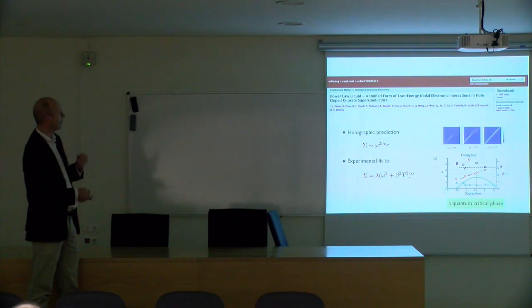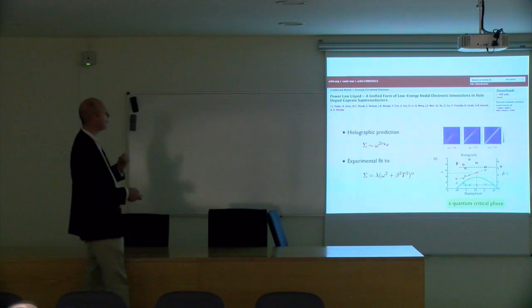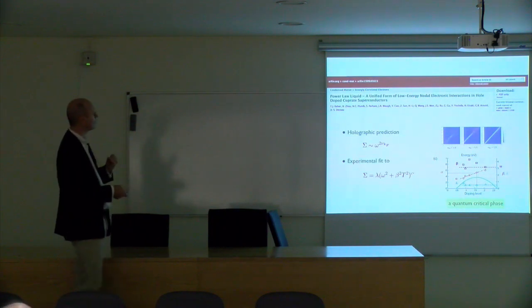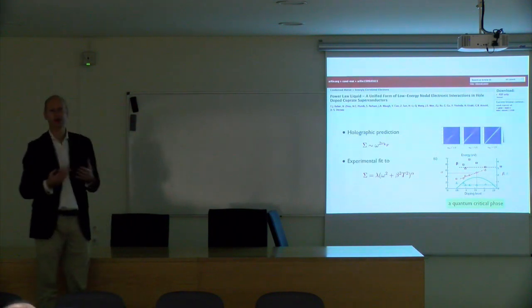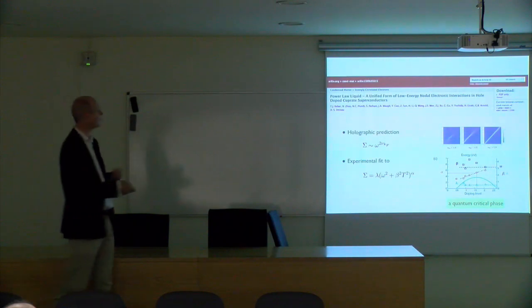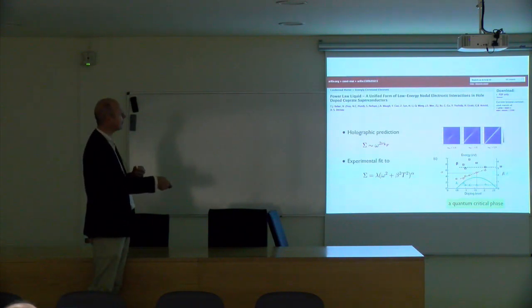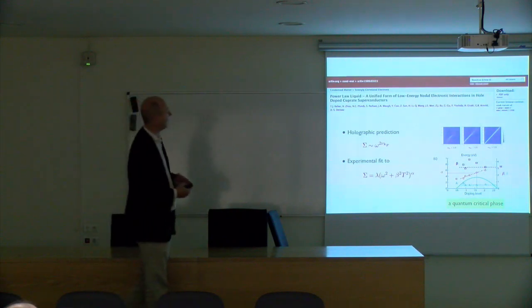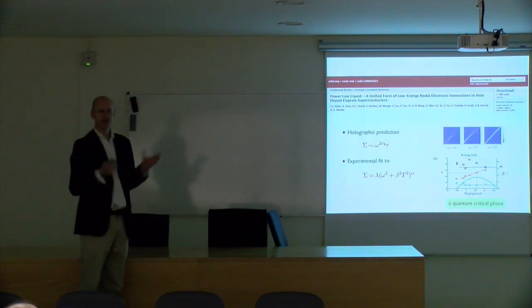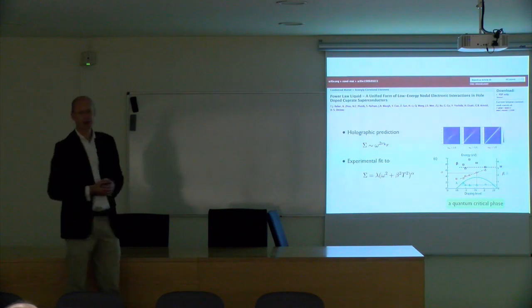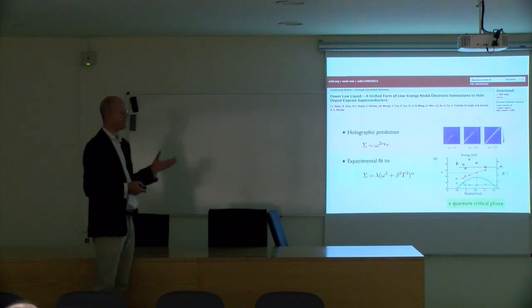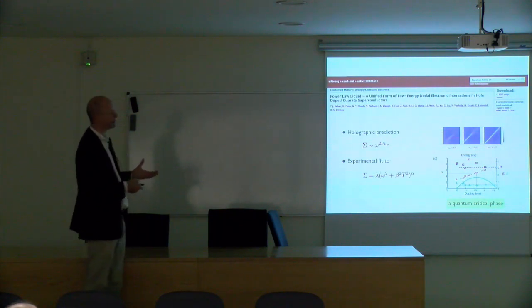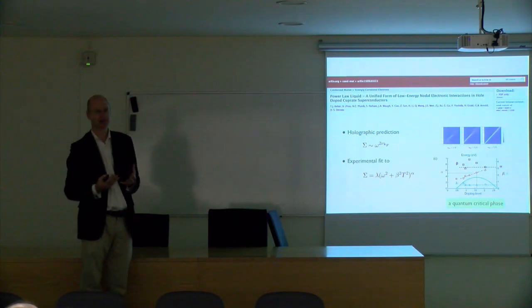And if you see what happens in this system, you find that as you change the doping, this alpha parameter actually changes slightly. Precisely at optimal doping, you find alpha as 1/2. That means it scales as omega to the 1. This is this marginal Fermi liquid story. But you also see that as the doping changes, it becomes a little bit less and a little bit higher than 1. This is the moment where anybody who works on critical phenomena should jump up and down, and say, this is very weird.